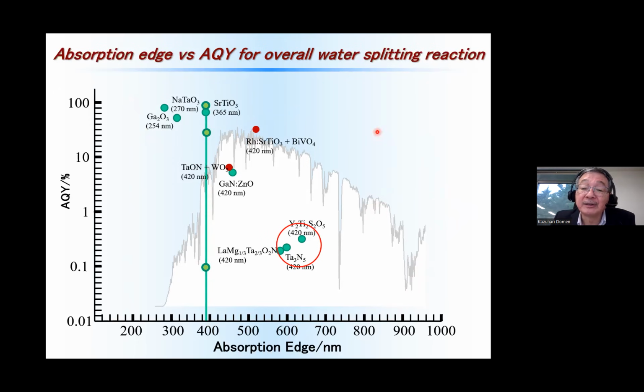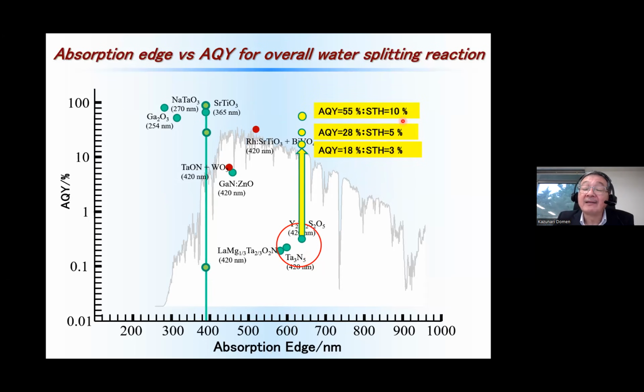And to achieve about 3 to 5% solar water splitting energy conversion efficiency, we need to use this kind of particles. I mean that the absorption edge is located longer than 600 nanometers. So we need this kind of photocatalyst. Then if we use, for example, this oxysulfide material to achieve solar to hydrogen conversion efficiency of 3%, we need about 20% AQY. If we would like to achieve 5%, this is a commercial level, we need to achieve about 30%. And to achieve 10%, we need to go beyond 50%.